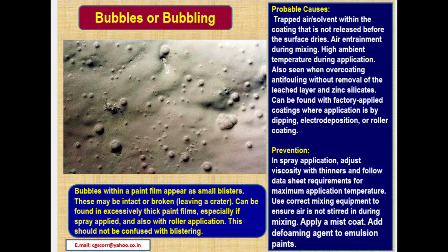Probable causes: trapped air, solvent within the coating that is not released before the surface dries, air entrainment during mixing, high ambient temperature during application, also seen when overcoating anti-fouling without removal of the leached layer, and zinc silicates. Can be found with factory applied coatings where application is by dipping, electrodeposition or roller coating.